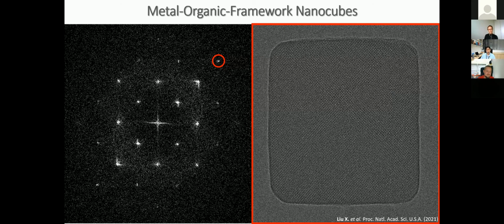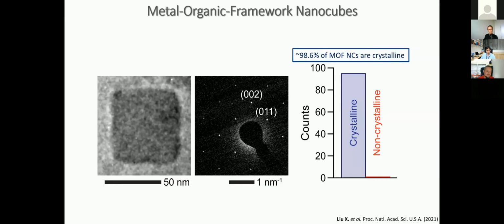Can we actually say so without having a high resolution image? Well, the answer turns out to be yes. So this is a cryo-TEM image of MOF, and we looked at, I don't know, like 98 cubes. Every one but one was crystalline. So every cube synthesized MOF, everything that had a cubic shape was a crystal, I mean, from the diffraction image. So the cubic shape is a very strong indication of the crystallinity of the MOF.